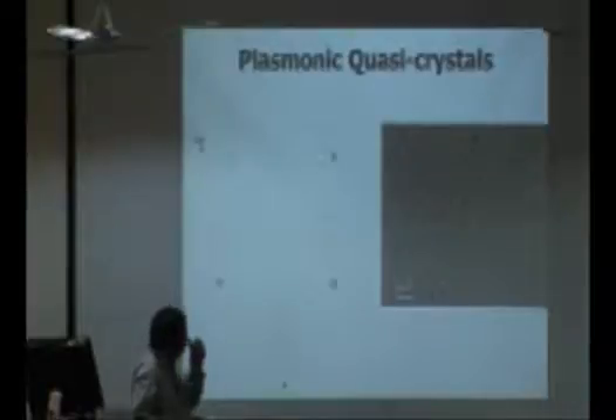So to remove polarization and angle independence in general, we are looking at plasmonic quasi-crystals. These are patterns made in gold. What we show is a simple way of designing and making these plasmonic crystals. For example, we made 1 millimeter by 1 millimeter square quasi-crystal structures which have about 6 million points.